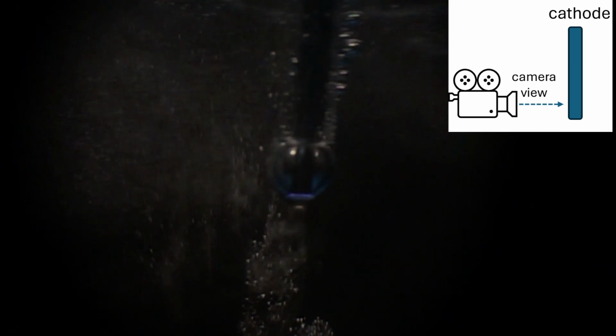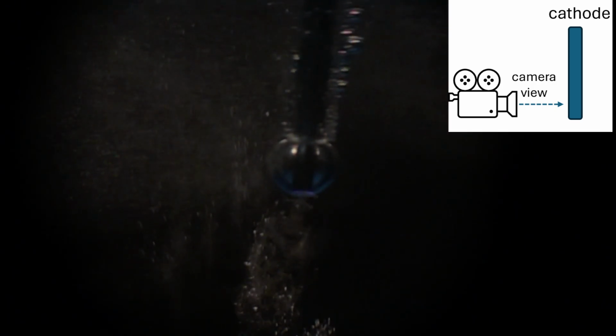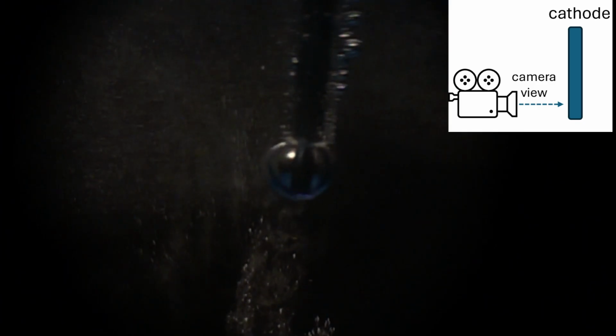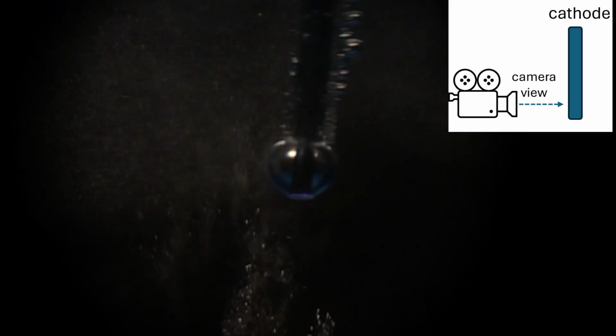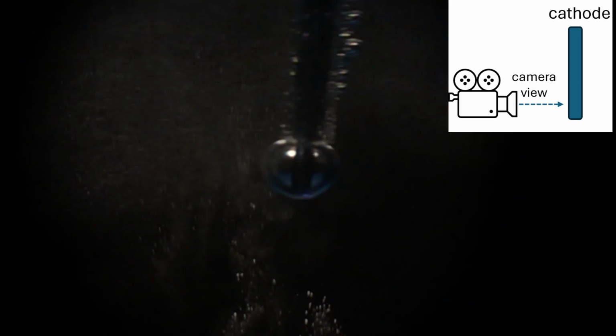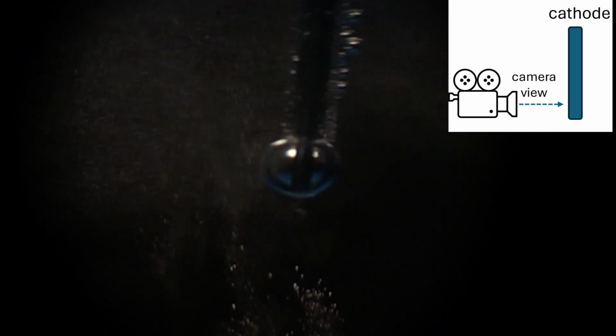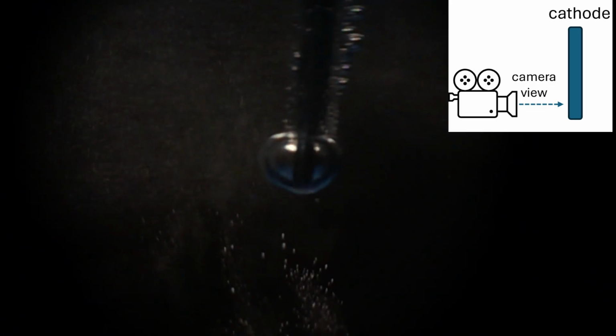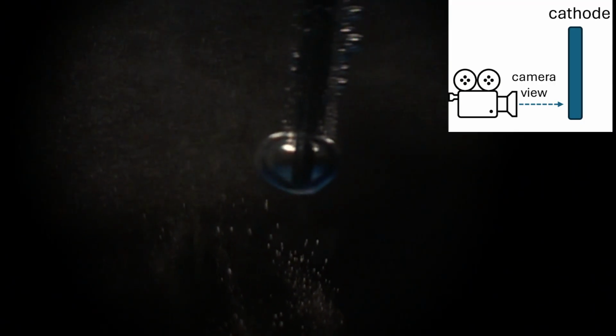Now this is at a sort of lower voltage, around 60 volts or so. And it's interesting because in this orientation specifically, because of that insulating sheath on the electrode, it causes this bubble to sort of form and stabilize around the electrode, at least when filming at 960 FPS. This is obviously happening very quickly, but this dynamic behavior is pretty consistent at this 60 volt setting.